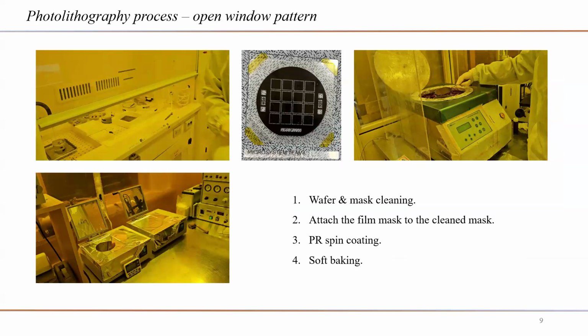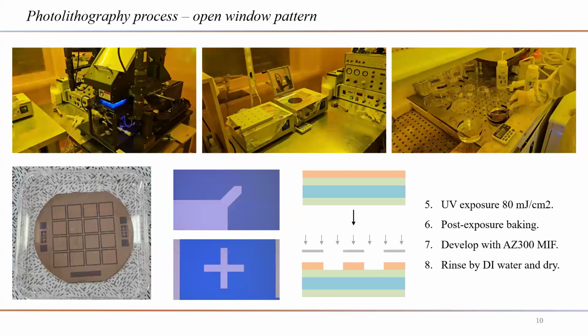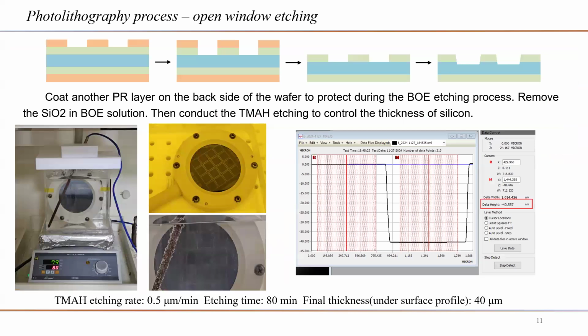Then the first process is to make an open window pattern, including PR spin coating, soft baking, UV exposure, and post baking. We develop the pattern and then rinse it. And then we do etching. In order to control the thickness of the silicon wafer, the first step is the BOE etching process to remove the silicon oxide of the open window pattern. And then we did the TMAH etching to remove the silicon and control the thickness of the silicon.